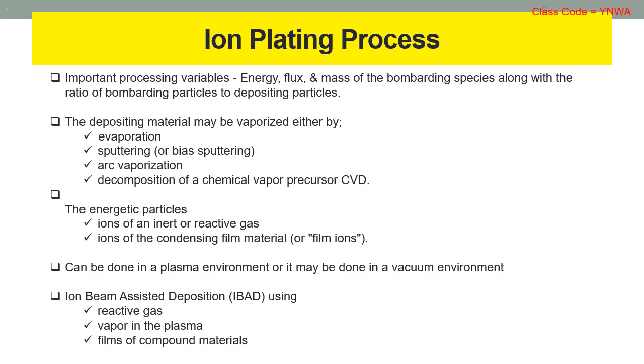Ion plating can be done in a plasma environment, where ions for bombardment are extracted from the plasma, or it may be done in a vacuum environment, where ions for bombardment are formed in a separate ion gun. The latter ion plating configuration is often called ion beam assisted deposition, IBAD. By using a reactive gas, or vapor in the plasma, films of compound materials can be deposited. Ion plating is used to deposit hard coatings of compound materials on tools, adherent metal coatings, optical coatings with high densities, and conformal coatings on complex surfaces.